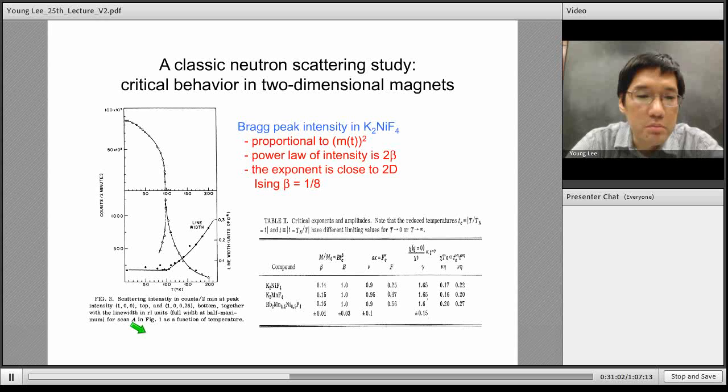And what's plotted on this upper panel is the intensity at one of these magnetic Bragg peak positions, and up here it's at the 100 position, and you see that below this Tn, again it's around 97 Kelvin, you have this upturn in the Bragg intensity for the scattering.